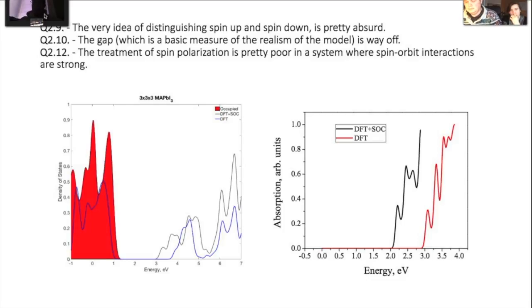And so also showing the absorption for these values with and without the spin-orbit coupling. You can see that the initial onset is jumping from about 3 to somewhere around 2 eV. So we're getting closer to the actual values themselves. And I think if we would even shift over one more, either include multiple K points with the spin-orbit coupling, or just take a single point spin-orbit coupling at the R point, you would see that band gap reduce even further, matching that of the experimental.